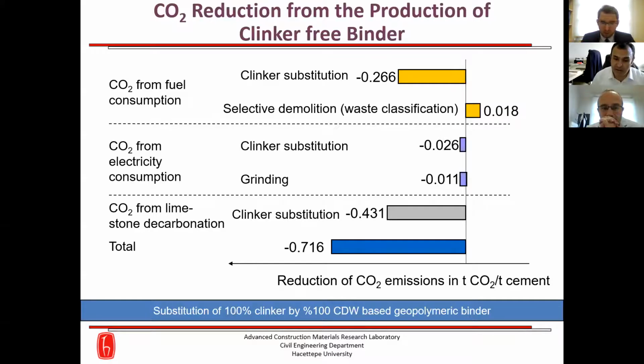And by far, the greatest saving effect is produced by the reduction of the raw material related CO2 emission from the limestone. As you know, limestone is one of the main raw materials of the Portland cement. It causes a significant amount of CO2 emission, around 430 kilograms CO2 per ton of the cement. Therefore, if we replace the Portland cement clinker with 100% construction and demolition waste-based material, a reduction of more than 700 kilograms of carbon dioxide per ton of the cement is obtained. This means a 90% reduction. This is a huge amount of reduction in CO2 emission.